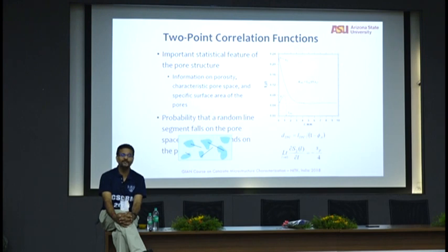Because for pore surface, there's absolutely no other way to determine the pore surface area. You can do BET. BET will give you some numbers, but you can't be sure because you're crushing it, so you don't get the entire pores. This is the only way. And so, again, see, it's a combination of some techniques, but the technique by itself is not capable of doing it. That's why I want to bring this up. The technique by itself is not capable of giving you the answer. You have to throw in some smart mathematics also with the technique. And there's no software that really will do it, so you have to write your own code.